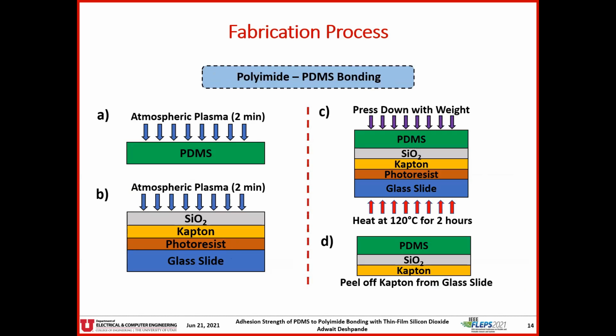PDMS and the SiO2 side of Kapton were treated with atmospheric plasma for 2 minutes and immediately brought in contact with each other. This stack was then pressed and heated at 120 degrees Celsius for 2 hours to allow the bond to strengthen. Control samples did not have any SiO2 deposited. They were, however, plasma treated and then pressed together and heated for 120 degrees Celsius for 2 hours for bonding. The samples can be removed easily from the glass slides with a gentle tug. 5 samples for each thickness for each deposition type were measured.